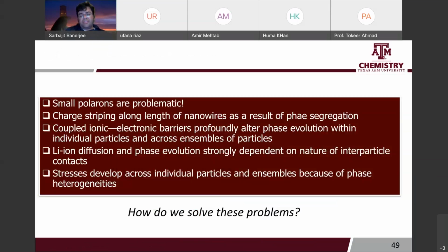So just to summarize this part, small polarons are problematic. We've located them, we've identified them as the source of the problem. I think anytime you solve a technological problem, you want to start by figuring out what is the problem really, right? We've seen things like charge striping along wires, including along curved wires, and this is a result of phase segregation, and it has some pretty large consequences on building up these stress gradients inside the wires that are directly related to failure mechanisms and loss of capacity.